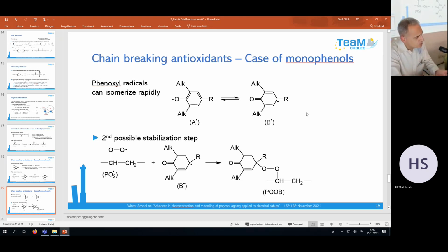But perhaps if we do a chemical derivatization, that means we make a reaction by a gas treatment of the sample, and this gas reacts with some carbonyl groups in order to form new peaks. It is possible to have a chemical deconvolution of the carbonyl peak, and to precisely quantify each carbonyl group. We don't do that in the case of stabilized polymer. So I cannot answer.